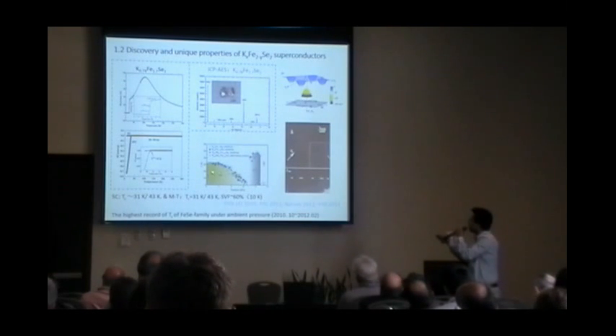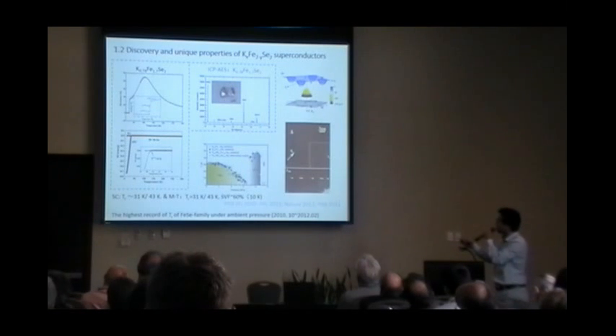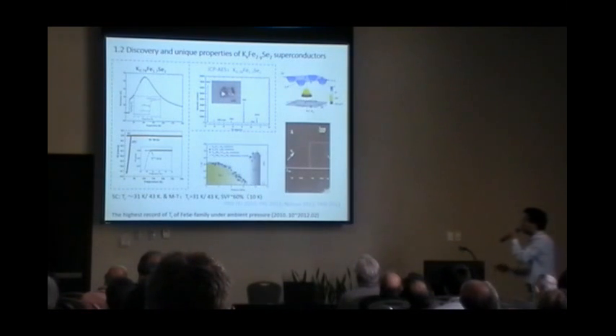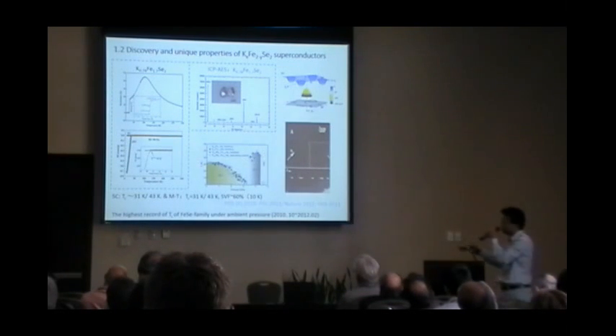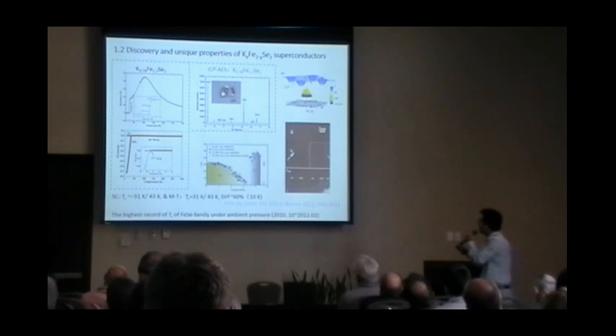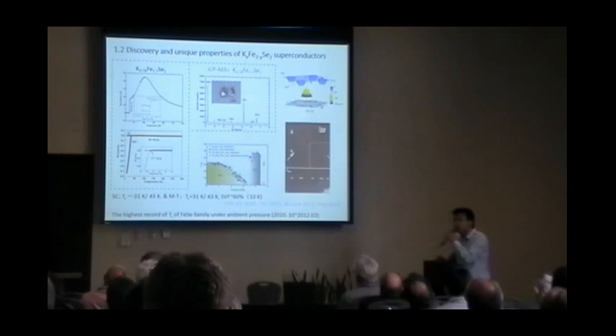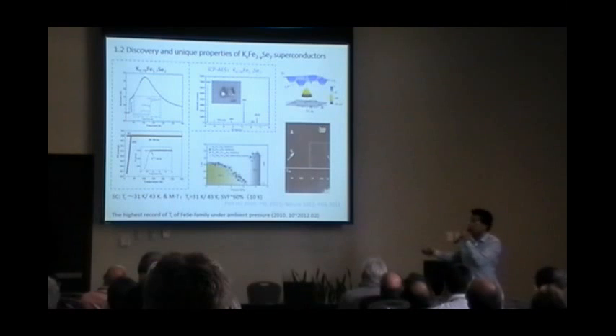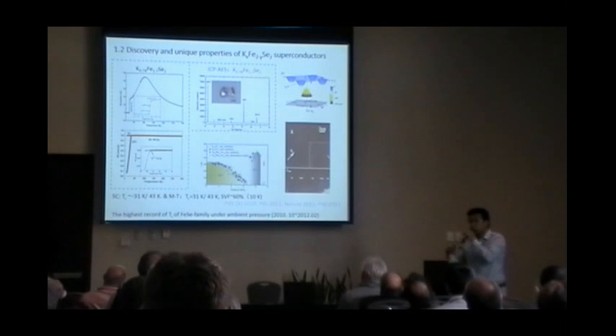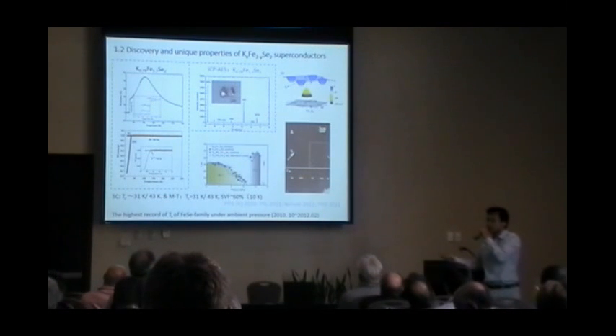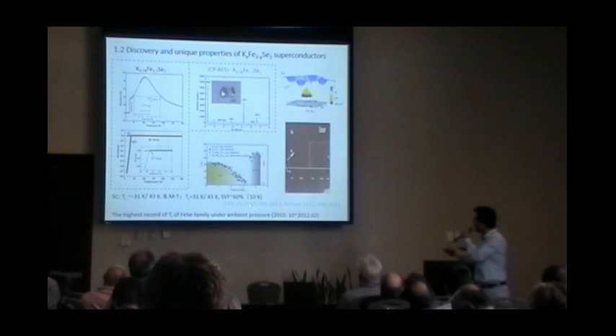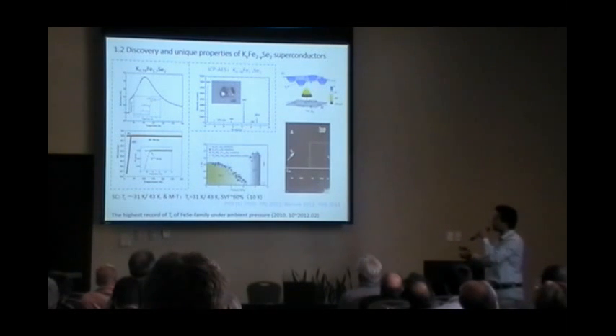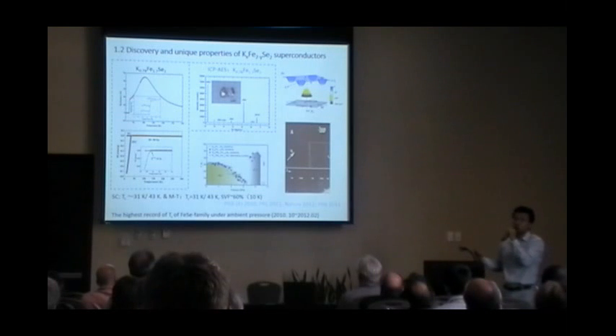Another experiment: we did some high pressure measurement on this sample. Around 12 GPa, a second dome shows up, and the highest TC is around 50K. But there is a very bad feature about this sample, the so-called phase. The phase is mixed. It means one phase is the real superconducting phase, and another one is a semiconductor phase. Up to now, even though it's been almost 6 years, we still don't know which phase is the real superconducting phase.